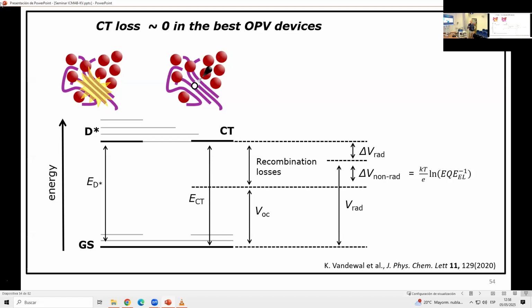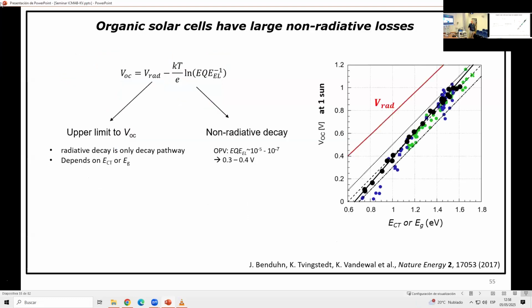So let's see if we can also do this. Here I plot basically, this red line would be the highest voltage we could get for a given gap or CT state energy. And the dots are where we really are. You can see that the dots are far from the red line, but maybe they're getting closer if you are at higher gaps. At least I see this, maybe you don't see this so clearly. But then you have to believe me, these dots are closer to the red line than these. There's a lot of noise on it.